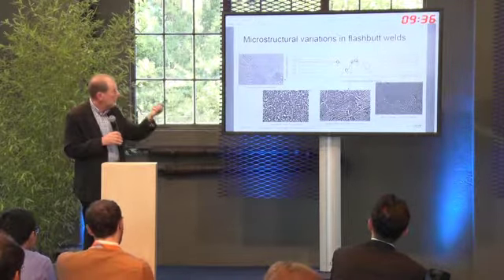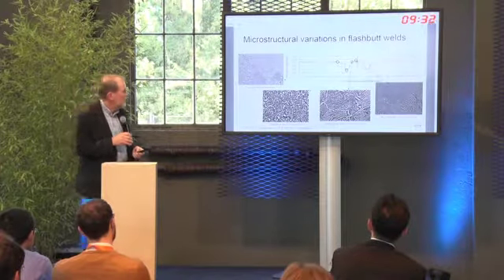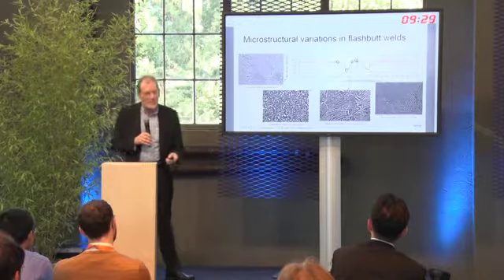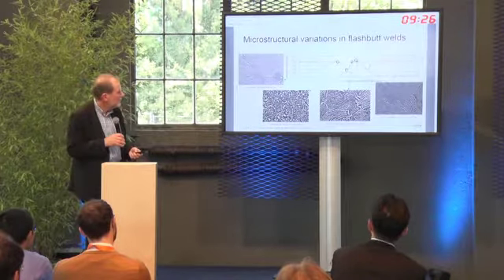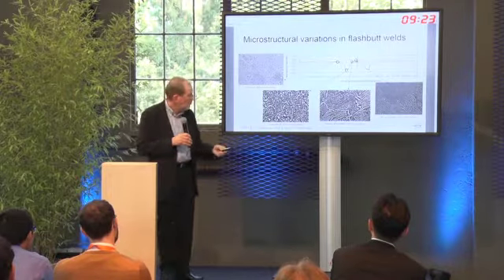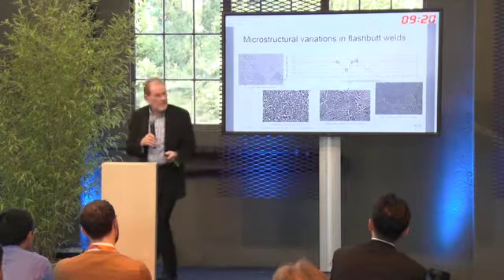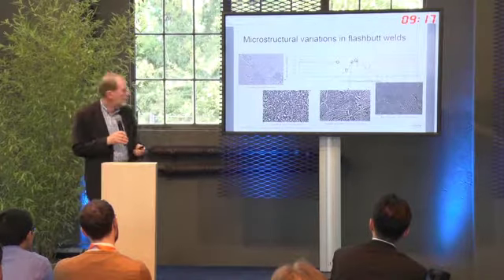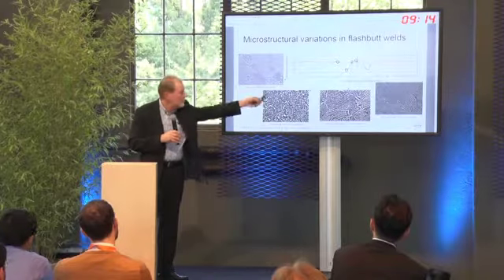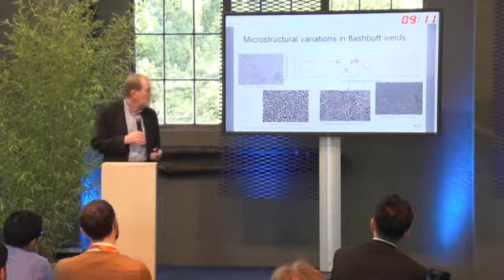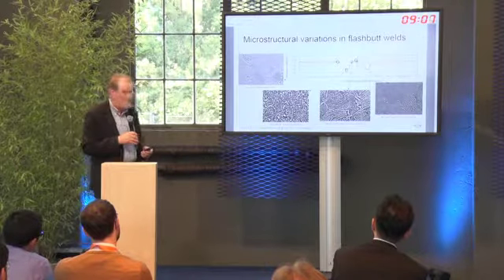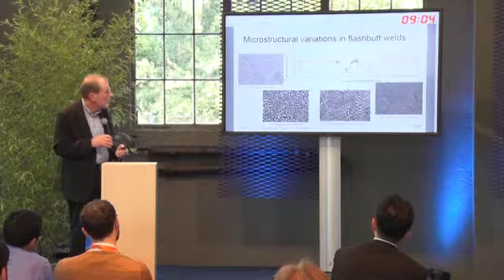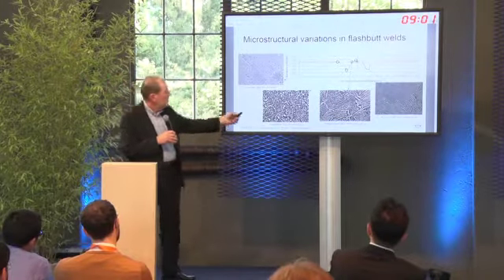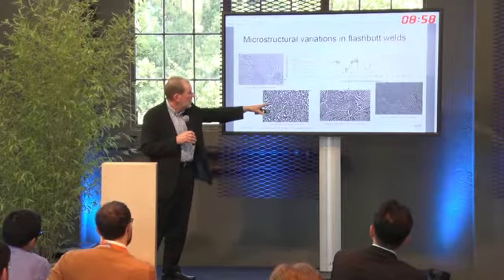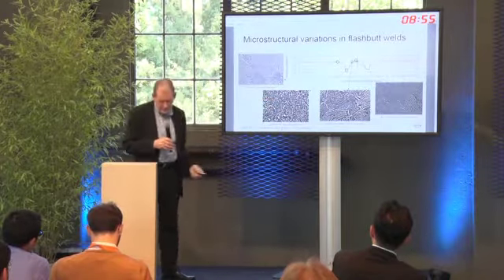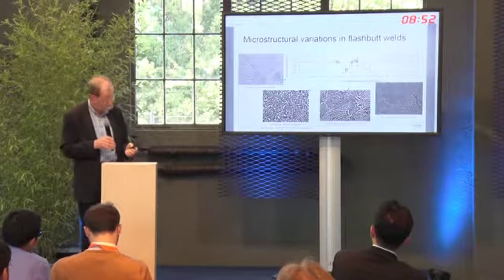near the bond line. So typically very similar pearlitic microstructures. As you move away from the bond line, you see the pearlite, or the cementite, is starting to spheroidise. This is a 1% carbon grade, so you can see evidence of the heavier cementite that might form around the grain boundaries. And then you've got this animal here in the softened zone, which really has not much there to pin the dislocations when you start plastically deforming it. And if you start playing around with the hardness distribution, you may not change that lowest point, but what you might change is the distribution over the rest of the microstructure.